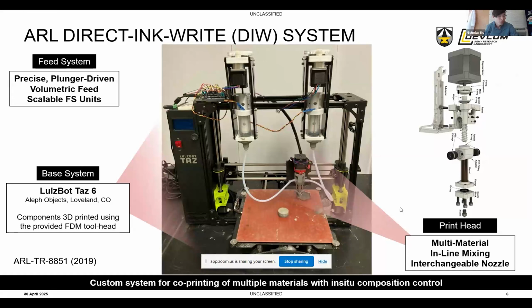So we actually built our own, where we took a Lulzbot TAZ 6, an off-the-shelf FDM printer, cannibalized it to make an XYZ control gantry, and then created this feed system where we can load our ceramic slurries or paste, think a clay-like material with the consistency of toothpaste, into those syringes that you can see up on top. And then those 2 stepper motors up above them would volumetrically deliver material down through those tubes into that singular print head. You can see that print head exploded on the right-hand side, expanded.